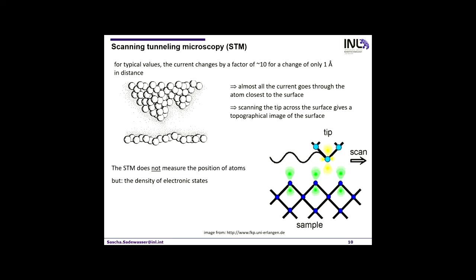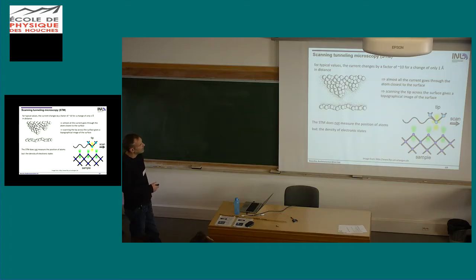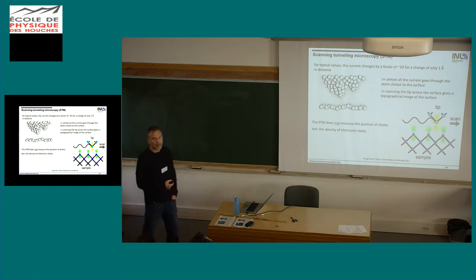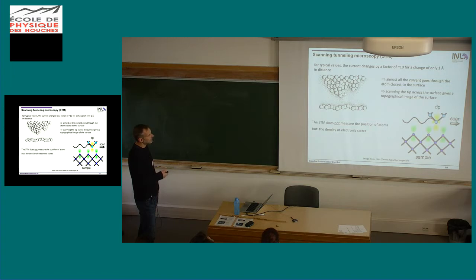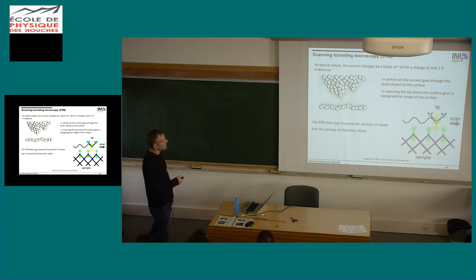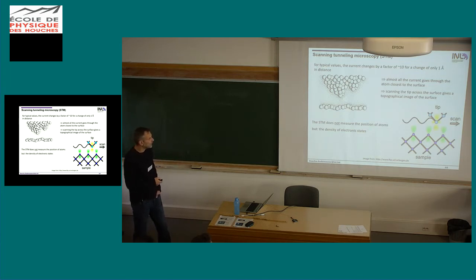So if you look at the numbers a little bit, then you realize that the current changes by a factor of 10 for every angstrom in change of distance. So you're very sensitive to the distance here. And that at the same time means most of the current is going through your last atom. So if this atom is only 1 angstrom behind this one, further away from the sample, then this one only contributes 10% of the current to the whole thing. So we get very sensitive to the foremost atom on the tip.